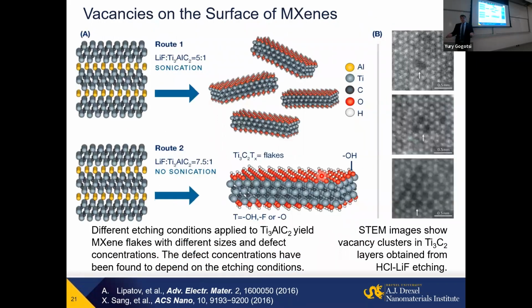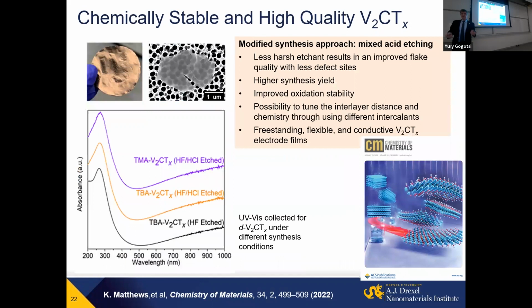Properties can also be controlled by introducing defects like vacancies on the surface. They're good for some applications like catalysis. We can, for example, also embed single platinum or other atoms in these holes, making single atom catalysts. For some other applications, they're not necessarily good. They may decrease the environmental stability of these materials. So you need to control this. And for a while, MXenes have also been plagued by moderate environmental stability. Some of them could be processed in solution for weeks. And when you make a film, for example, I have pictures of paper sheets with my signature in MXene, made just by filling a fountain pen and signing it a few years ago, and they're still conducting and black. But in solution, they would hydrolyze after a while.